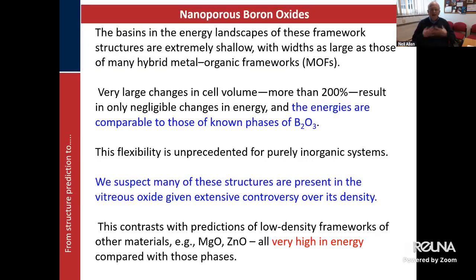Now, historically, and I should say this is before my time, back in the 1960s, there was a huge controversy about the density of molten B2O3, because it seemed that depending on how you prepared it, the conditions, you could get a big variety in the density. Well, our results suggest why that will be, because there's lots of different forms. Depending on the conditions, you'll get different ones, and there's a lot of flexibility in the bond angles. So depending on the precise form you've made, the density may change quite a lot.